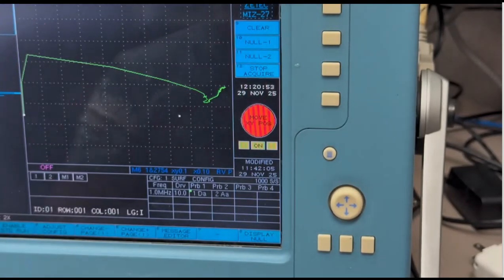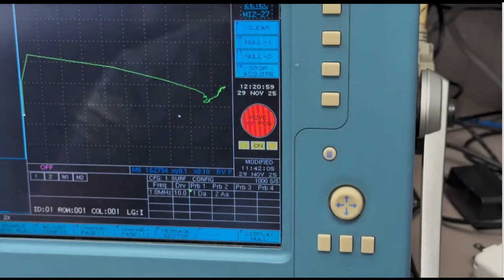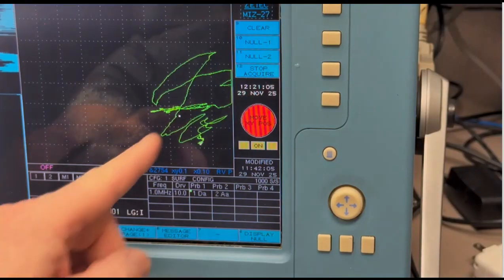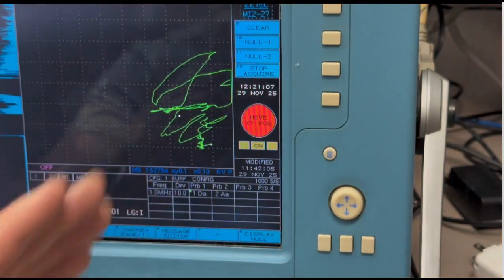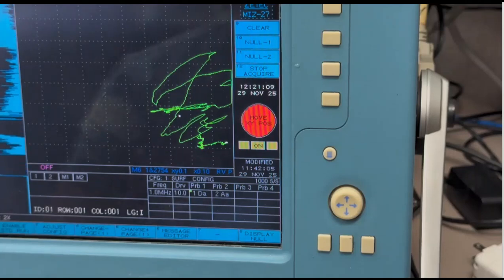Now we're going to double over the Reynolds wrap. So now I've got two thicknesses of Reynolds wrap. And you'll see that's our signal right there. So now even more phase lag. And now it's down to probably 40%.